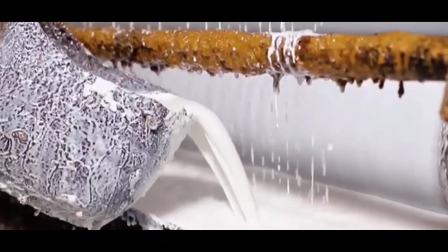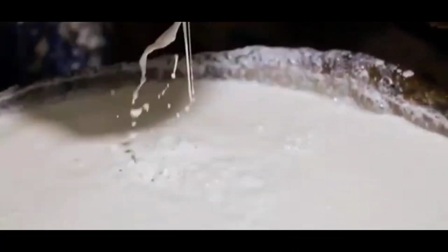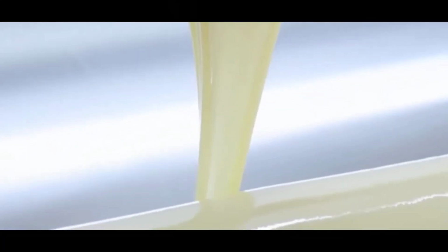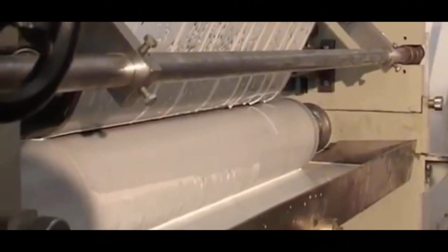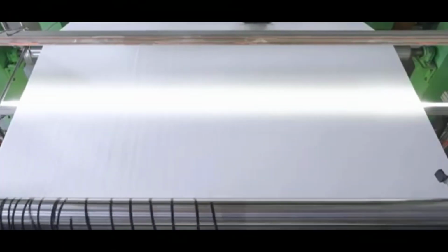Depending on the type of tape, the adhesive may be water-based acrylic, known for its durability, heat resistance, and aging stability, or synthetic rubber, which provides instant tack and greater flexibility across various materials. The adhesive is continuously stirred inside a sealed mixing tank to maintain consistent viscosity before passing through the coating rollers and a fine steel blade that regulates layer thickness with micrometer precision.